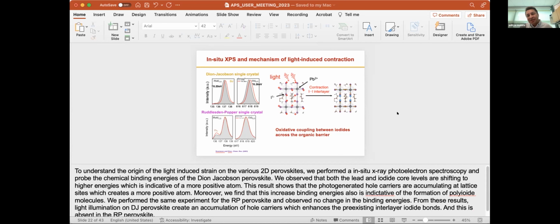So we don't think that this is really inhomogeneous, because really what we are measuring is bulk properties in the device, right? Okay, yeah. And also in XPS, these are all fairly representative bulk measurements. So we think that this is a homogeneous effect which comes from the structure of this 2D perovskite.